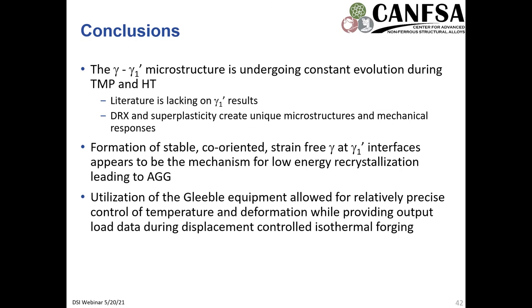So in conclusion, the primary gamma prime microstructure is undergoing constant evolution during this high temperature thermomechanical processing and the subsequent supersolvus heat treatment. The literature is kind of lacking on primary gamma prime results showing evolution at these high temperatures and during thermomechanical processing. It's treated more as a static feature of the microstructure that only changes during dissolution, and not in a way that includes a stable oriented gamma shell.